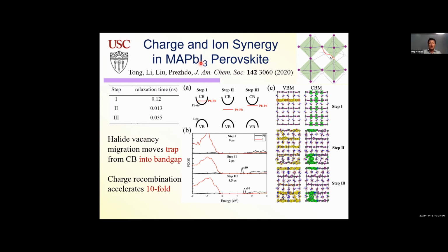most common defect. But for reasons of the electronic structure of this material, because of lead to a large extent, this defect creates no trap state. It creates a defect state inside the conduction band, but no mid-gap state. But it's very well known that in these materials, especially if you have electric fields present, in a solar cell for example, these defects can migrate.